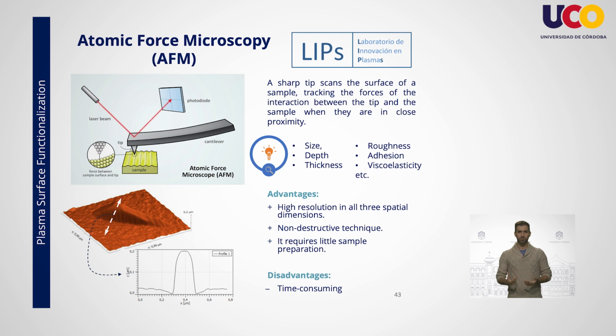In an atomic force microscope, a sharp tip scans the surface of a sample very closely, tracking the forces of the interaction between the tip and the sample by measuring the displacement of the reflection of a laser beam on the cantilever containing the tip. It provides information on size, depth, thickness, roughness, adhesion, or viscoelasticity, among others.